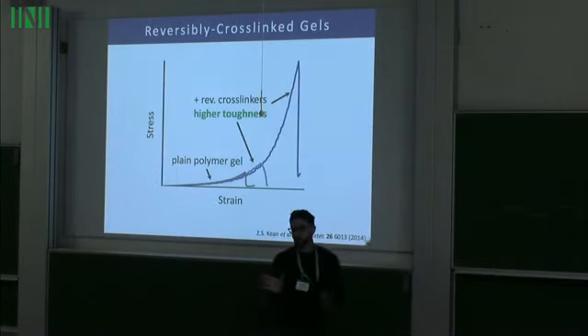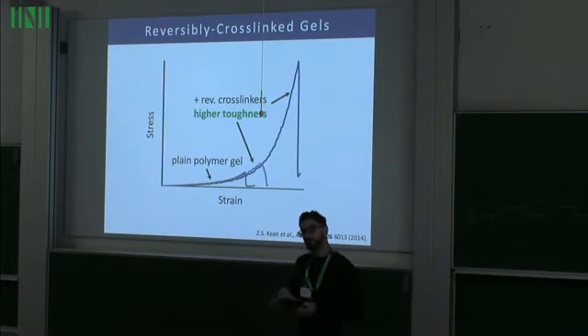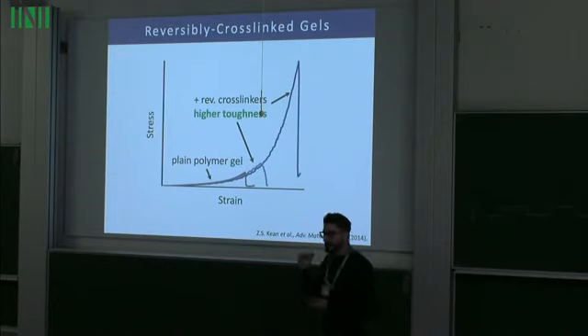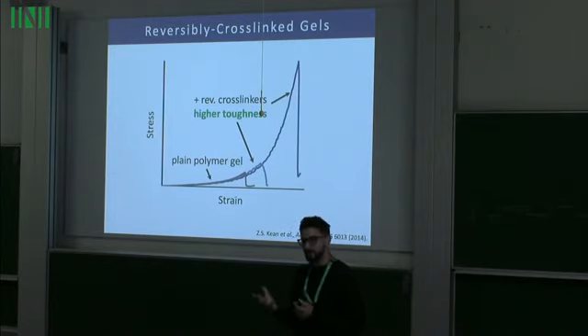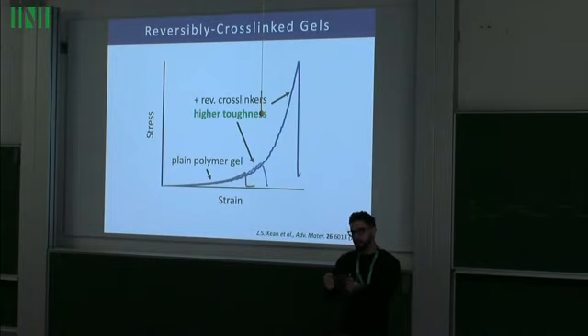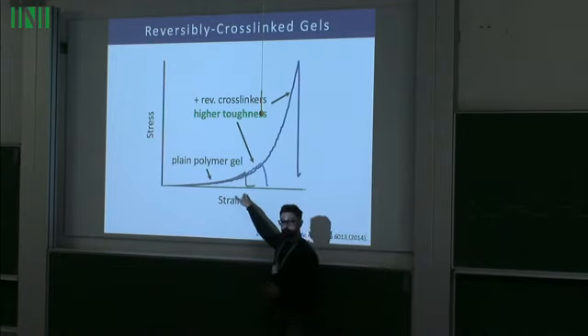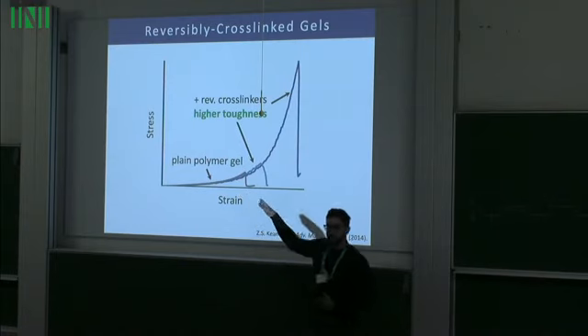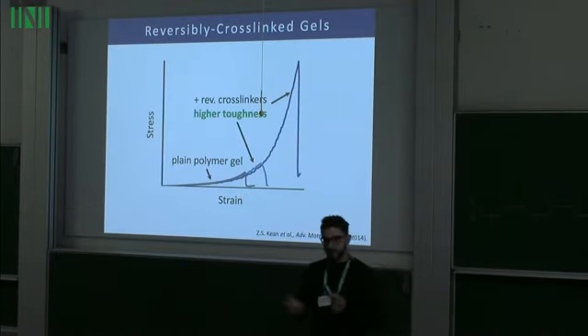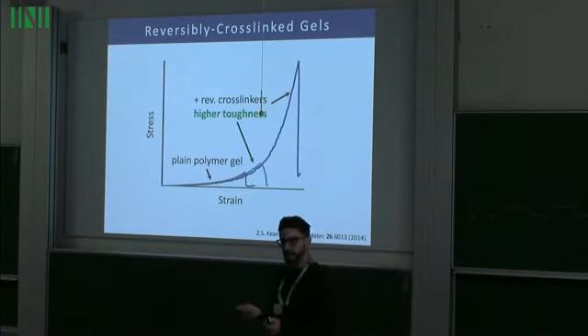It has no reversible cross-links. If I add reversible cross-links into the material, I get the light blue and the dark blue curves. What I find is that the material has a very similar modulus, or slope, or characteristic curvature to this stress-strain plot, but I'm allowing it to be strained more before it breaks. The breakage point is where this plot just falls off and crashes. Okay? So somehow these reversible cross-links are doing something to the mechanics of the network that allows this behavior.